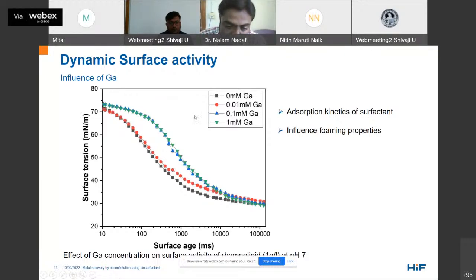So at a low gallium concentration of 0.01 millimolar, we can see the initial trend of surface tension reduction is very much similar to rhamnolipid alone, indicating that more free rhamnolipid is present in the solution and is predominant at the surface. Whereas in the later stage, we can see it differs from rhamnolipid alone, suggesting that the rhamnolipid-gallium complexes that are formed take some time to reach the air-water interface.